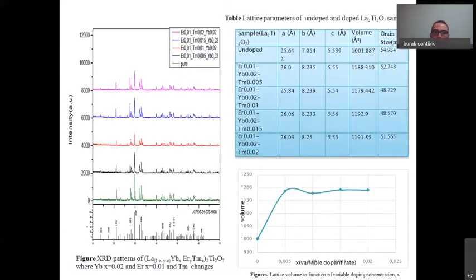Similar cases took place in the tri-doped samples as well. In here, we fixed the ytterbium and the erbium concentration, while the thulium concentration was changing. We wanted to show how the thulium concentration affects the optical results. And again, there were some slight shifts between the samples in the lattice parameters, but these results showed that the tri-dopants can also form a solid solution in the lanthanum titanate phosphors.